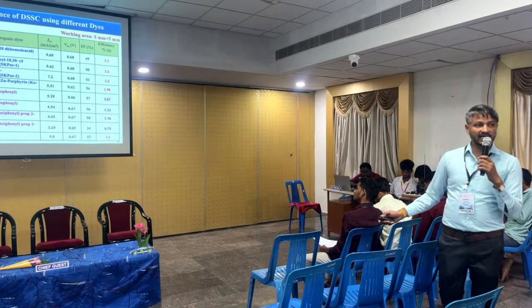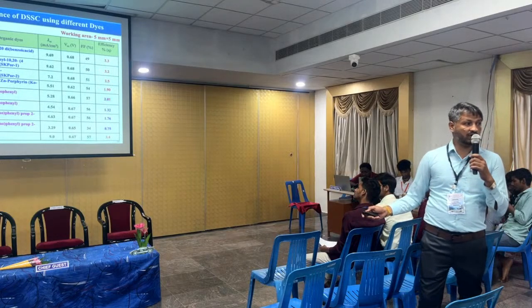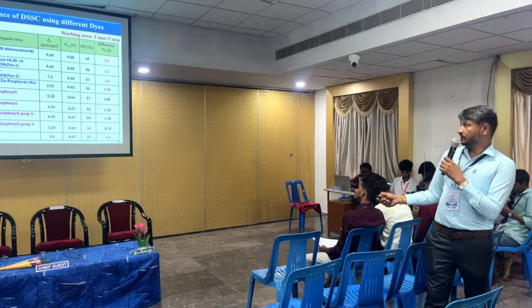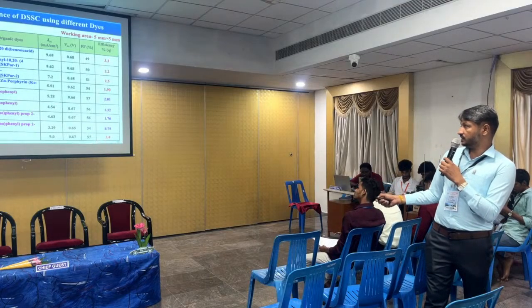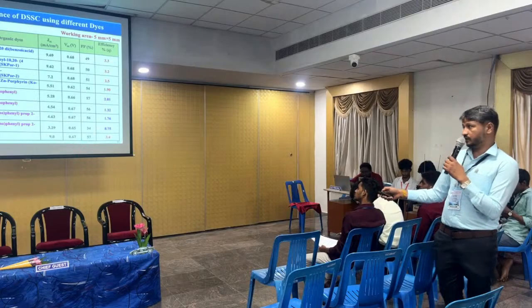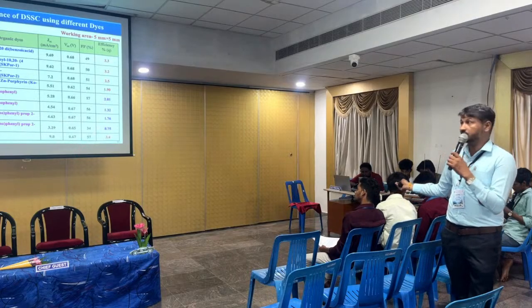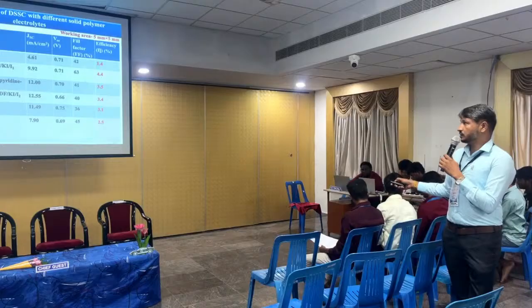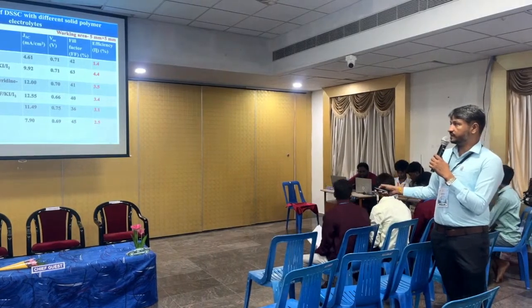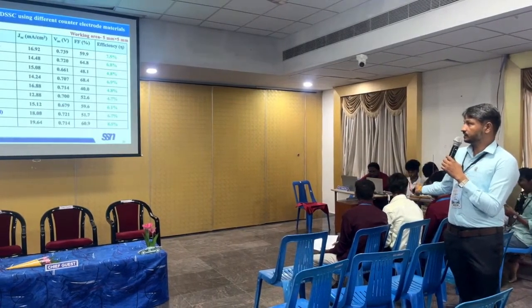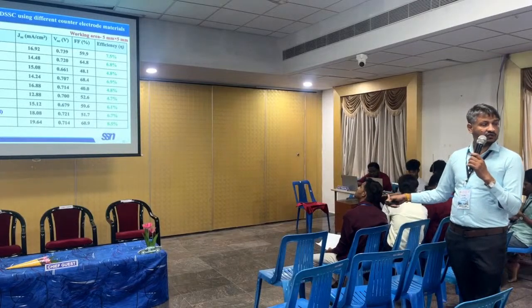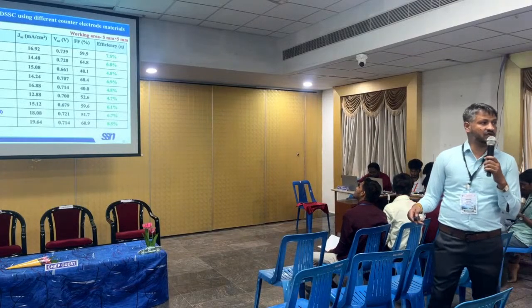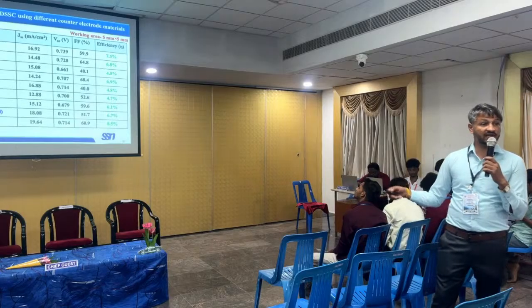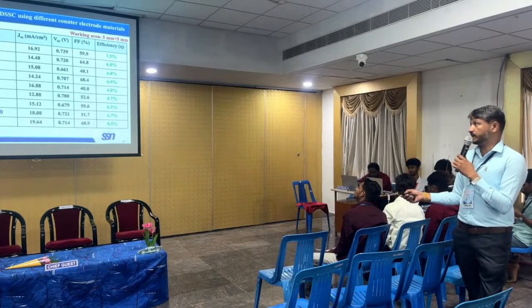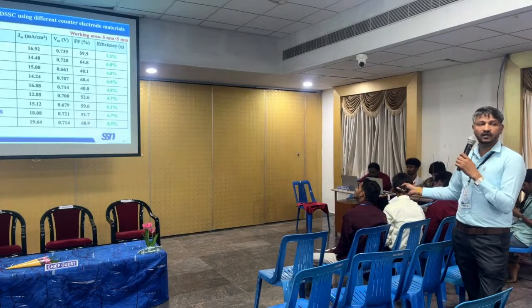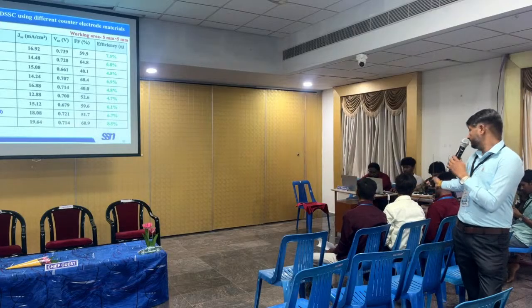Likewise, one of my colleagues also did a significant amount of work in dyes. You see the efficiency improvement. Of course, it is less, but making dye is not so easy. So electrolyte also we tried. Then counter electrode also, platinum is expensive. To avoid that, we introduced several other structures to get better efficiency. So maximum we got close to 7% efficiency.